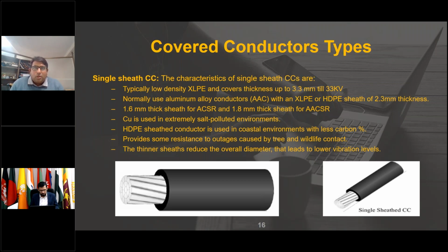So if we use copper, it is usually used in an extremely salt polluted environment, usually in what we call sea areas or coastal areas. Basically, mostly we use copper because it's an extremely salt polluted environment. So HDPE sheeted conductor is used in coastal environments with less carbon percentage. It provides some resistance to outages caused by tree and wildlife contacts. And the thinner sheet reduces the overall diameter and it leads to a lower vibration level. Those vibration levels may cause a lot of difference. So you can see the single sheet covered conductor just below this description.